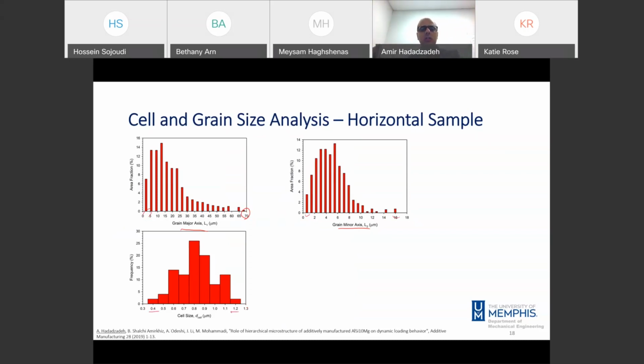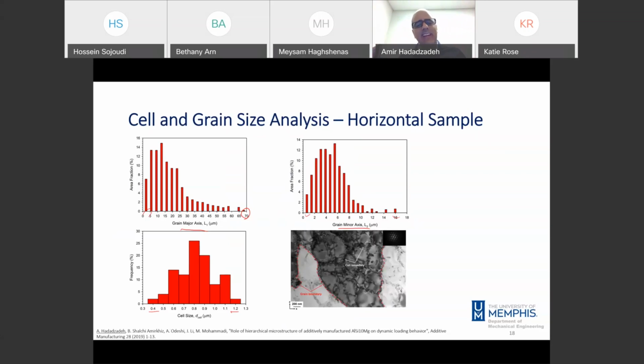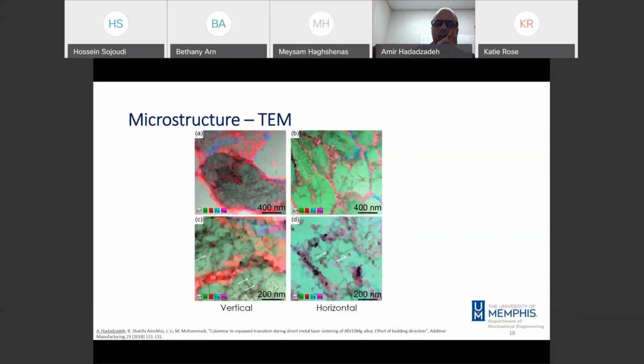So this is the first step of understanding the hierarchy in microstructure. Between grain structure and cell structure, there's at least one order of magnitude difference in the length scale. It means each grain consists of several cells, and we confirm that by TEM studies. So we study the sample by TEM, and this microstructure here shows the TEM structure in the 011 zone axis of the aluminum, and the red dashed line shows the grain boundary, and inside each grain we see several cells. That's why we see such a difference in the grain size and cell size.